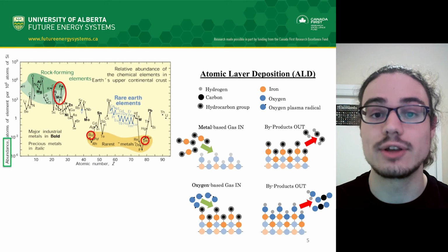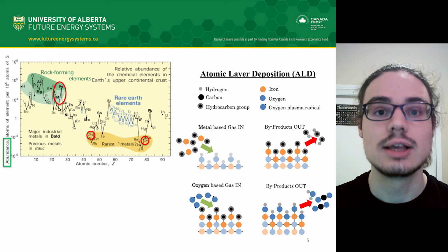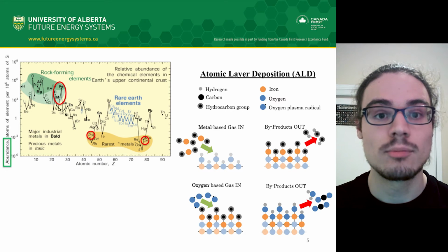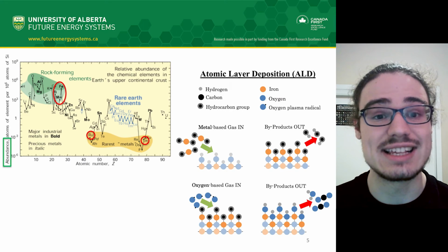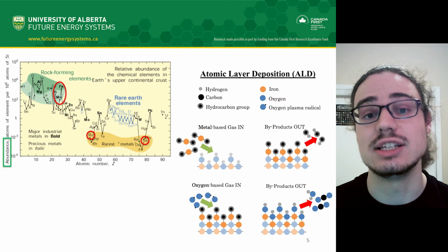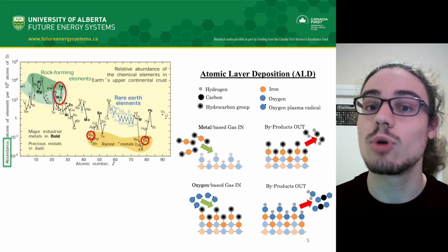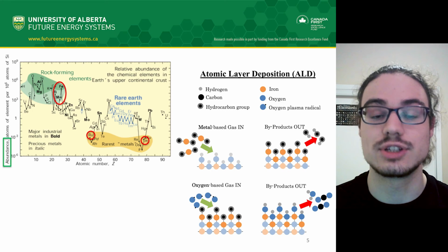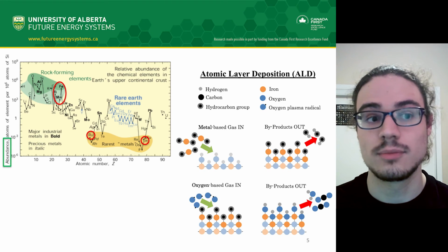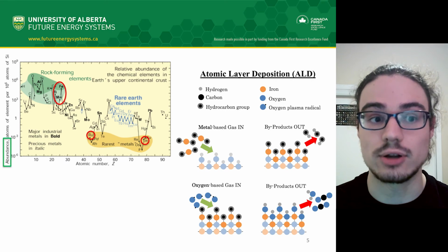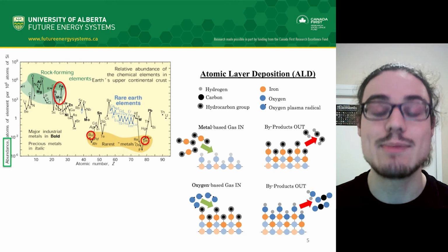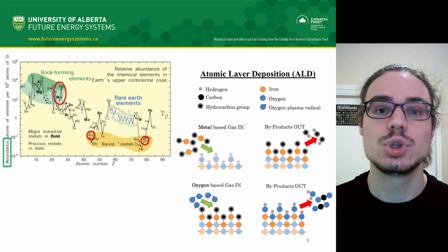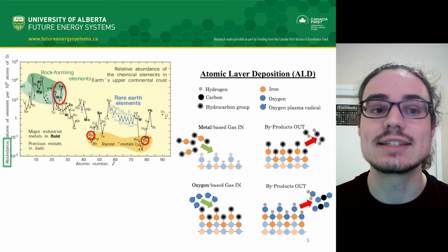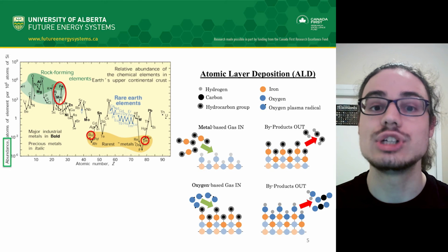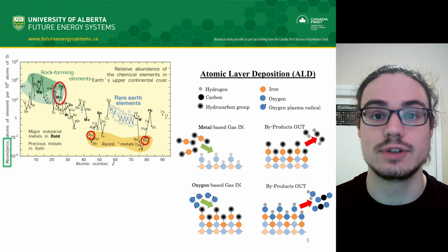When it comes to catalysts for Zinc-Air batteries, precious metals, such as platinum and ruthenium, set the bar. These rare earth metals can catalyze the reactions in Zinc-Air batteries quite well, but they reduce the accessibility of Zinc-Air technology because of their scarcity and high cost. Engineering more abundant and low-cost materials into catalysts for Zinc-Air batteries is truly the goal of my research. One of the contenders for non-precious metal catalysts are transition metal oxides, like manganese oxide or iron oxide. To engineer these materials as catalysts, we often synthesize nanostructures of the metal oxides, which have increased catalytic activity because of the abundance of surface area.